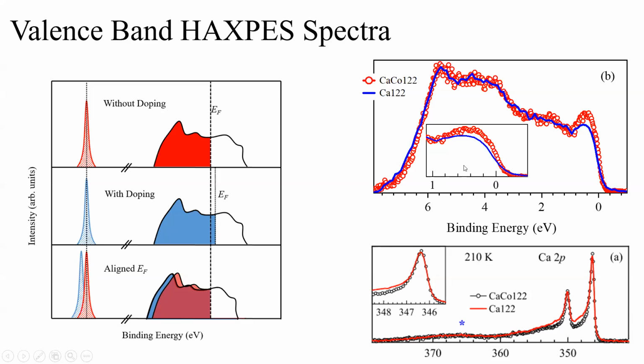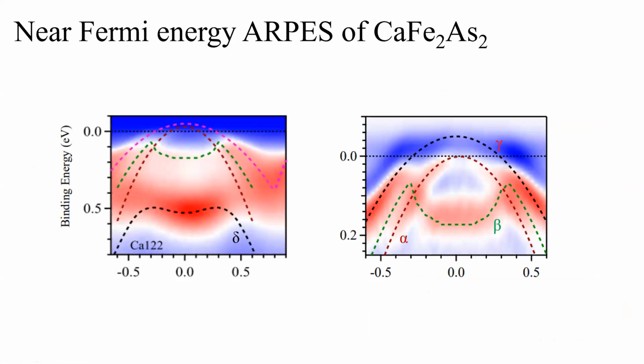But since we have doped in, we actually expect that this kind of feature should appear, which was not the case. And the same thing we can see here also. There is no significant change in the main core level spectrum. There is a small change at this position, but this is because of the surface state that we observed close to this energy value. If required, I can discuss it, but let us not discuss it.